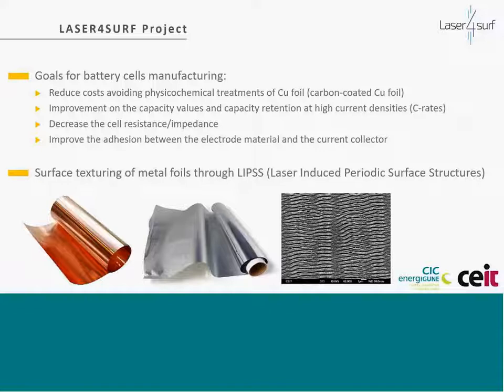So how are we going to do this? We are mainly doing this by texturing the metal foils, which look like the two rolls you have here on the slide. It is just a very, very thin metal foil, around 10 to 12 microns in thickness. And we produce what are called laser-induced periodic surface structures, which are periodic lines that are automatically defined on the surface of a material. You can see here in this micrograph, this is the scale bar for the image. This is 1 micron. So take into account that these lines have a period of, let's say, 800 nanometers, always below the wavelength of the laser we use. So we can produce very, very precise structures on the surface of the metals that can improve the performance of the current collectors.